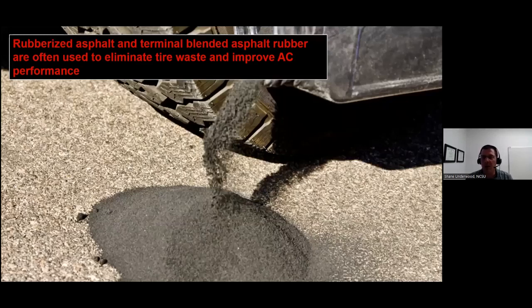So crumb rubber, we use about 15,000 tons, that's US tons, in the US. In the case of rubberized asphalt, those dosage levels are usually around 20 to 25%, coupled with a gap-graded asphalt gradation. The state of California has been championing the use of terminal blended asphalt rubber in dense graded mixes at dosage levels in the order of 5 to 8%. They are not necessarily getting the benefit from the performance of the rubber at those low dosages, but they definitely get the environmental savings of finding a positive reuse for the rubber materials.